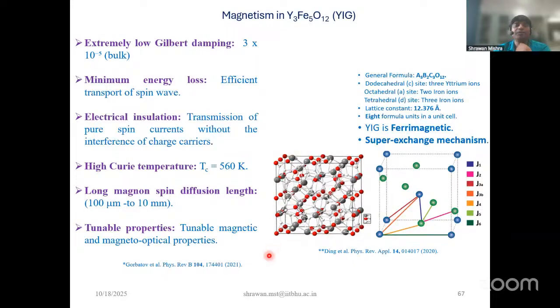But nevertheless, this has most of the benefits that are required for magnon-based devices, such as very low Gilbert damping. So it can reverse its direction very fast. Minimum energy loss, that's a welcome thing, because we want energy-efficient devices. And also it is insulating in nature, that's another benefit. High TC, that's again an advantage, because you can make room temperature devices. If your material's transition temperature is very low, no matter how beautiful that material is or what exceptional property it shows, making any devices is not a very feasible option.